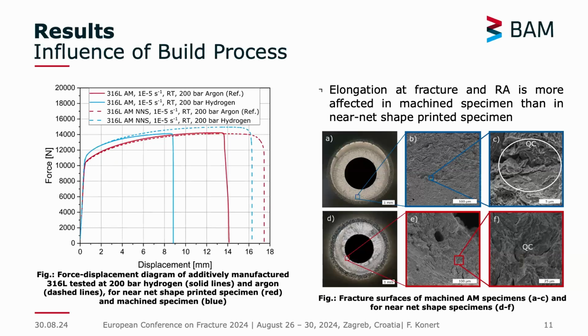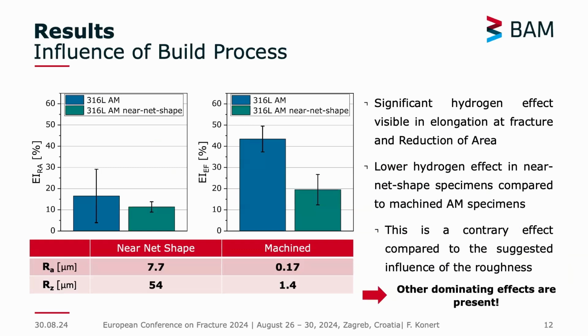So as you can see for these specimens, there are also quasi-cleavage areas in the fractured surface, as well as for the near net shape ones. And if you take a look at the surface roughnesses, the near net shape ones, of course, are way worse than the machined ones. So it's a bit of an opposite trend. If we just relate to the surface roughness, we would assume that the near net shape ones would just perform worse in hydrogen, but of